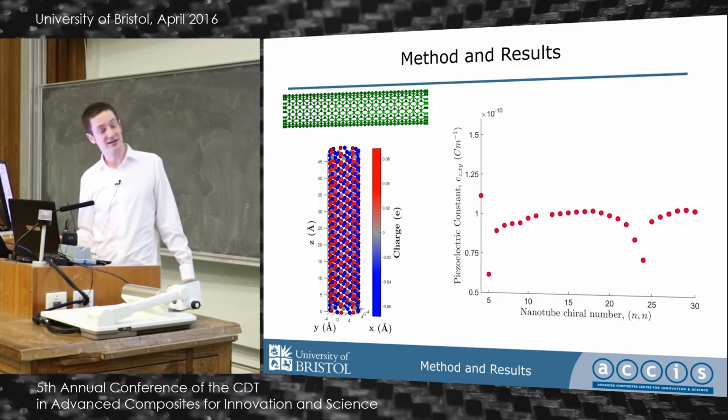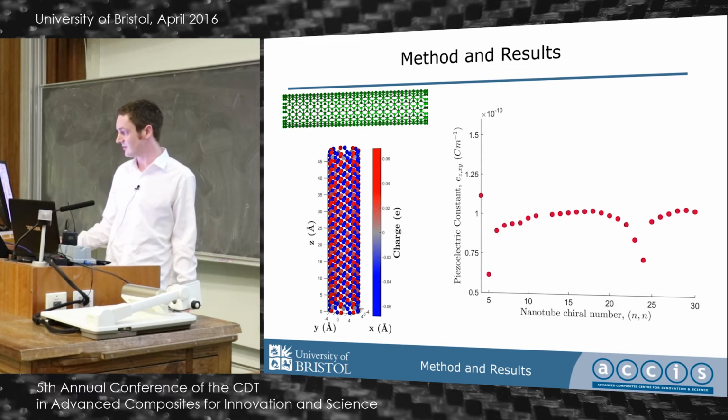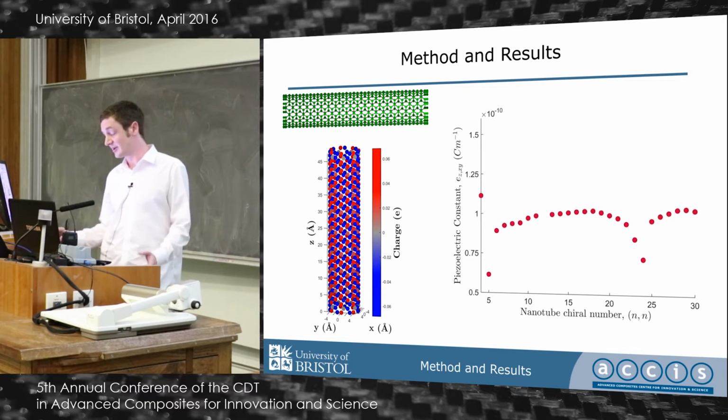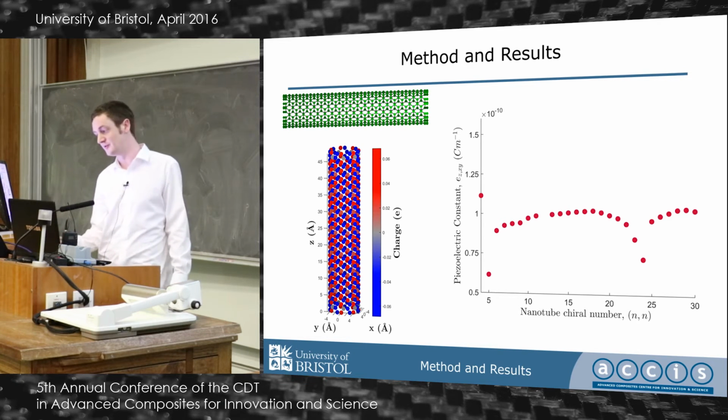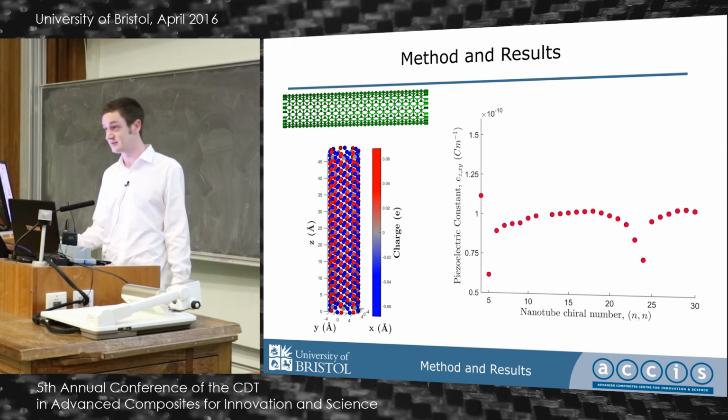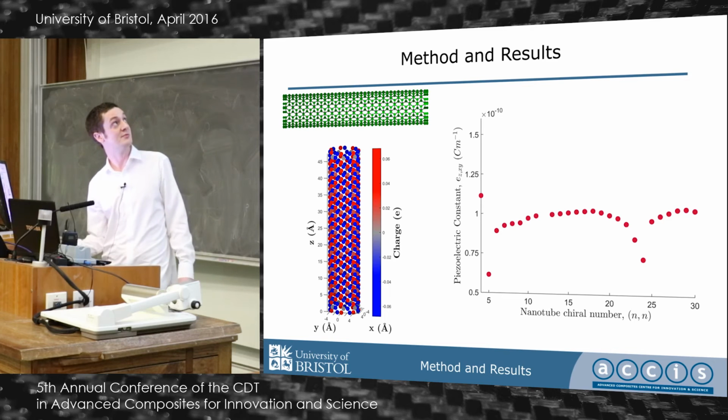So instead, we use a mixed method, whereby we take a frame structure and model it in FE, with the atoms becoming the nodes of the structure and the molecular bonds becoming beams. For the beam properties, we have to borrow some constants from molecular mechanics. And once we take this, we have a deformable standard FE sort of structure that we can deform, work out where the atom's going to be, calculate some charges for these atoms, which is also slightly more complicated than it sounds.